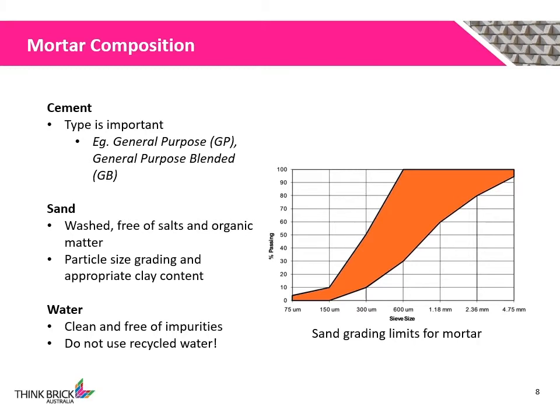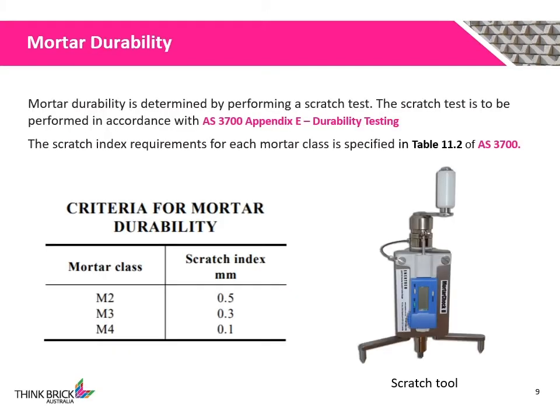The water used shall be clean and free of impurities. If these conditions are not met, durability and strength issues can arise. Mortar durability is determined by performing a scratch test. The scratch test is to be performed in accordance with AS3700 Appendix E, Durability Testing. The scratch index requirements for each mortar class are specified in Table 11.2 of AS3700.